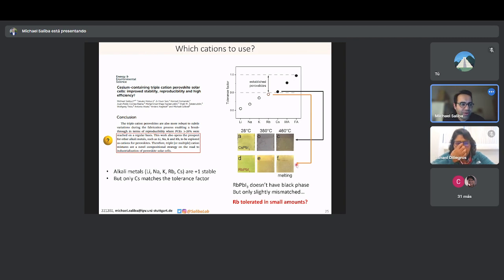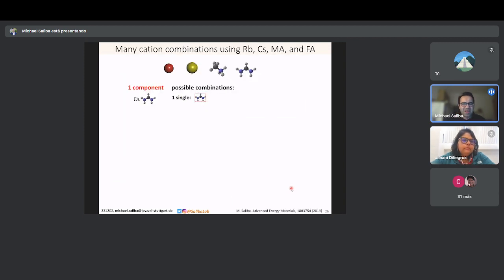So then the idea was, since our mixing approach previously was working extremely well for us, how about using small amounts of rubidium in this kind of mixing approach? But then how do we mix? So I always wanted to keep formamidinium because it's high temperature stable and it's causing the most redshifted band gap without using tin yet.